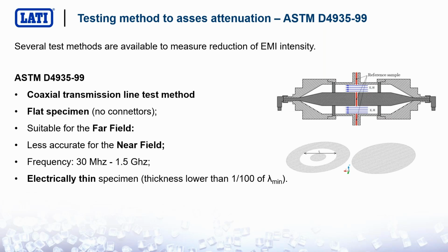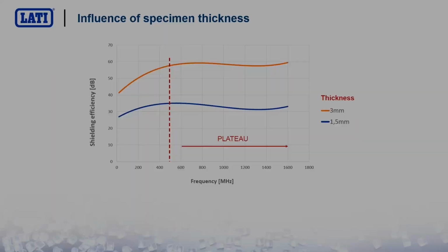It worked perfectly for a frequency between 30 MHz and 1.5 GHz, and it is also suitable for so-called electrically thin specimens, meaning that the thickness of the specimen must be lower than 1/100 of the minimum wavelength of the incoming signal. We tested specimens 1.5 and 3 mm thick. As I told you before, the University of Aachen took care of all these measurements on our material.